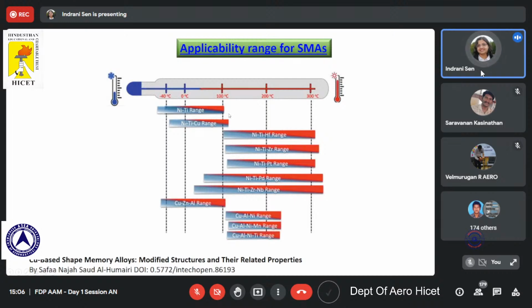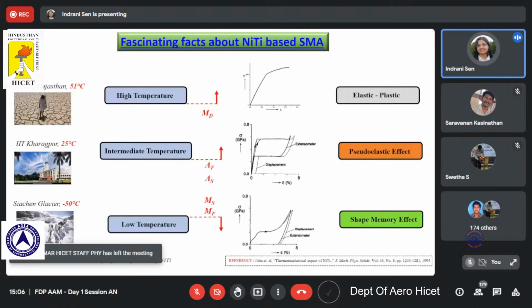If we want to use it at a higher temperature range, we can make a ternary nickel titanium alloy with the addition of hafnium or zirconium or platinum, and we can achieve a temperature as high as 300. So overall, we can achieve quite a range of temperature, starting from minus 50 to plus 350 or 300. That is quite a high range of temperature that can be obtained. On the other hand, copper-based alloys are mostly high temperature, and we cannot use them for low temperature or room temperature applications. So all this has made nickel titanium very important.